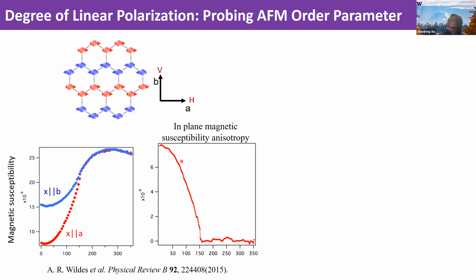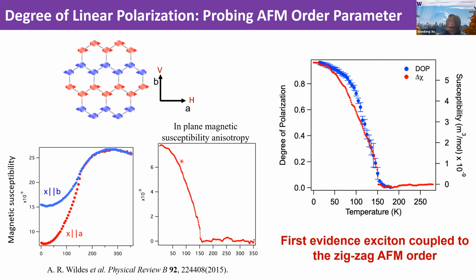Then we can overlay the degree of linear polarization in the PL, which is the blue dots, with the in-plane magnetic susceptibility anisotropy, the red dots, as a function of temperature. Now you can see that the degree of linear polarization resembles this order parameter. So you can say this is strong evidence that the exciton is coupled to the zigzag antiferromagnetic order, and the optical anisotropy is coming from these zigzag magnetic orders.